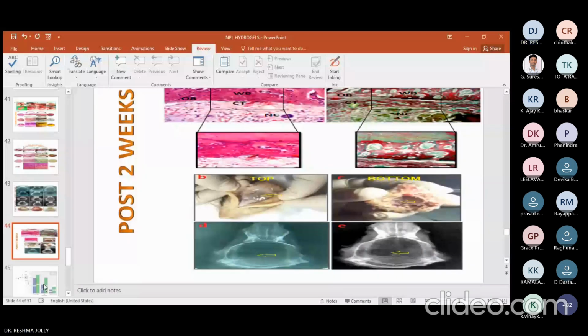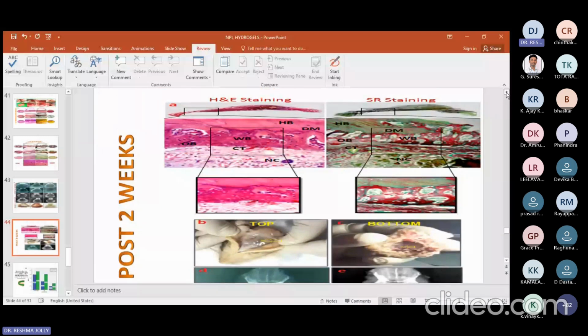These are the 2 weeks results which I wanted to show you. If you are getting woven bone in the damaged part, in the defect, it is a very good sign. In our case, we got the appearance of woven bone after 2 weeks. You can see this. This is woven bone. This is HE staining, this is SR staining. Woven bone should be visible as early as possible. It means your material is quite biocompatible with the host bone. So in our case, after 2 weeks, the woven bone has started occurring.